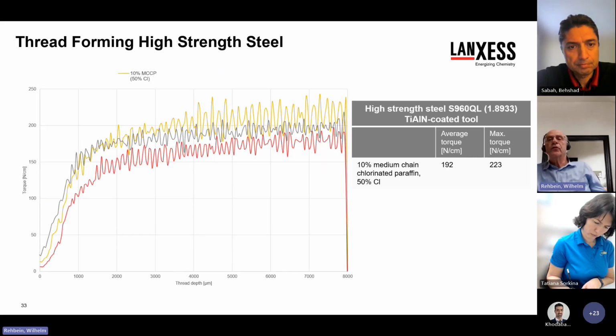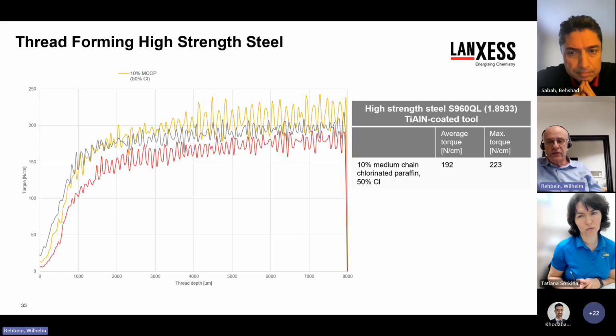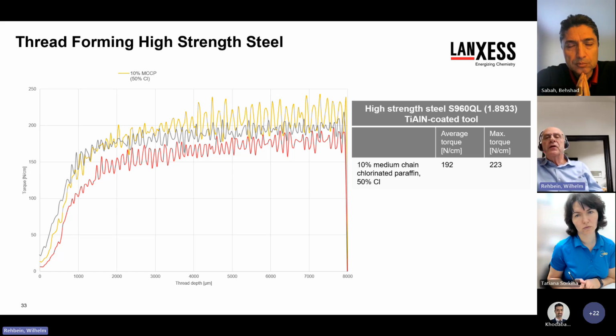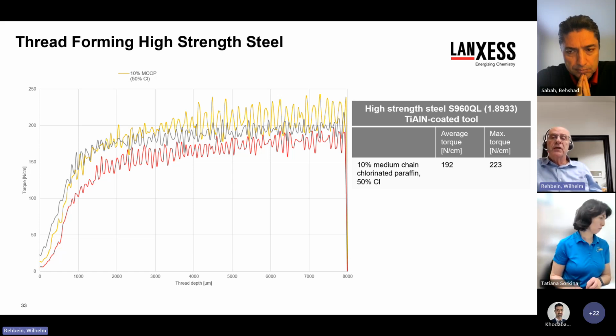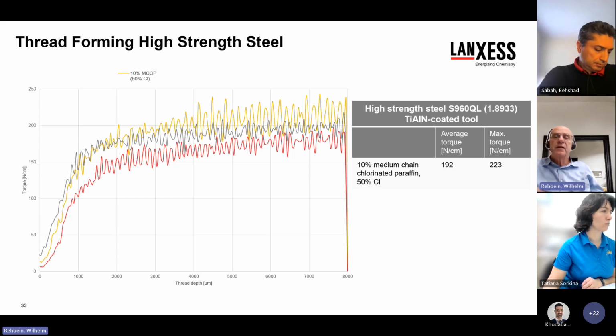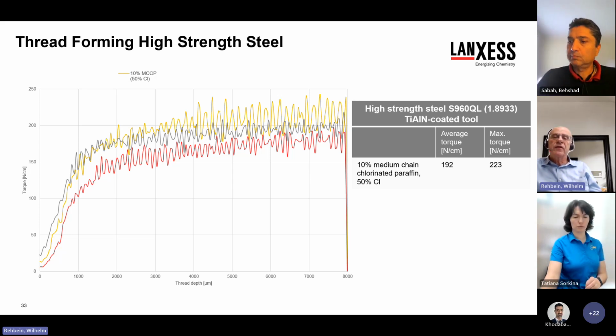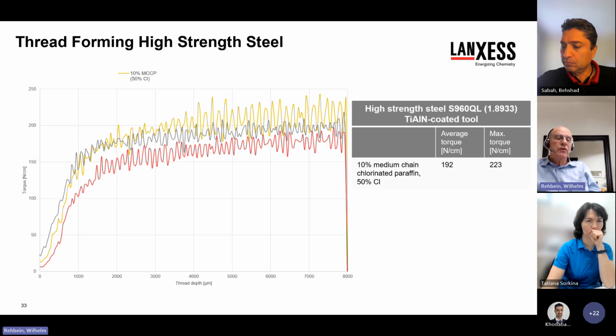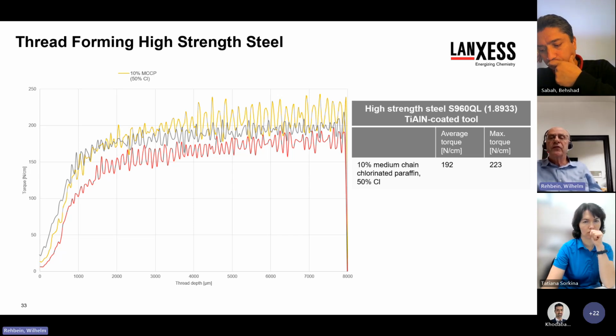We did the thread forming also in S960QL high strength steel. The yield strength and the tensile strength of S960QL are similar to ultra high strength steels that are commonly used in the car industry. So therefore they are quite difficult to machine by forming processes. When running the test with this steel, the medium chain chlorinated paraffin showed a comparatively high torque, and the curve, as you can see, is quite uneven. With the sulfurized ester, and even more with the sulfurized triglyceride, same treat rate, the torques are much lower, which means that the forming process will be less energy consuming and also cause lower tool wear.